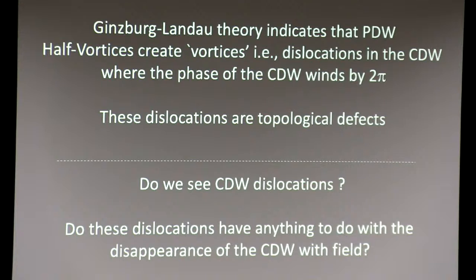So what you really should be looking for is areas of your sample where the charge density wave order parameter also winds, and these point dislocations, the density of these point dislocations should increase with increasing magnetic field. So the question is, can we see these point dislocations where the phase of the order parameter actually winds - this is not superconducting, remember, this is the charge density wave order parameter winding by 2 pi. And do these increase as you increase magnetic field? And does this have anything to do with the mechanism by which the charge density wave disappears as a function of magnetic field? So in the next few slides, that's what I'm going to show you.